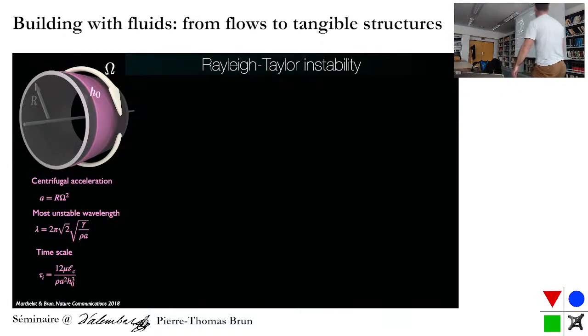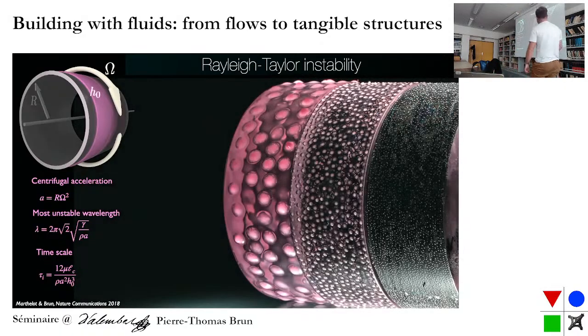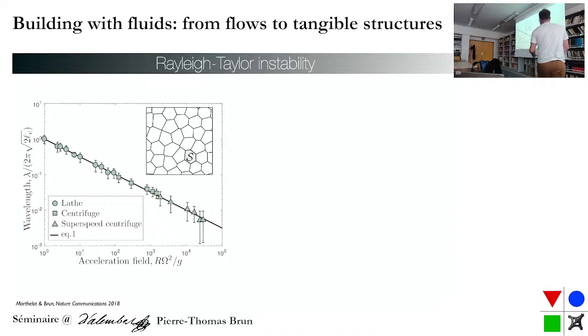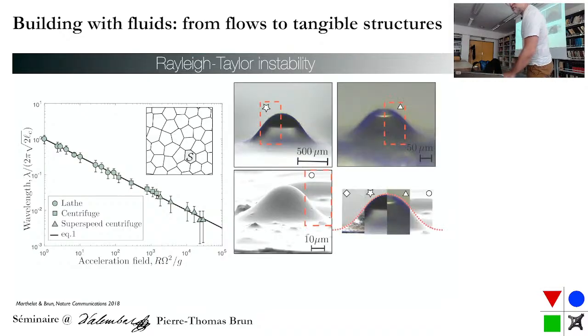another source of acceleration. And so in that case, we use centrifugal forces. So we coat the outside of a cylinder, and if you coat the outside of the cylinder, the physics remains the same, but basically, the faster you rotate, the smaller the drops you will obtain. Okay, but again, the physics remains the same. So I go a little bit fast, but essentially you can change the acceleration by orders of magnitude, and then you change the drop size by an order of magnitude too. Unfortunately, there's a square root, so of course you work hard.